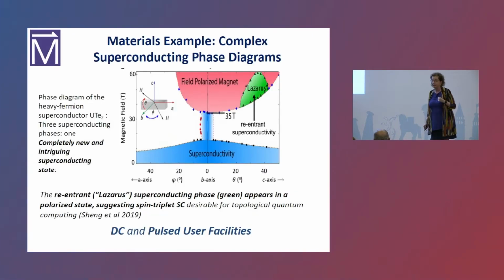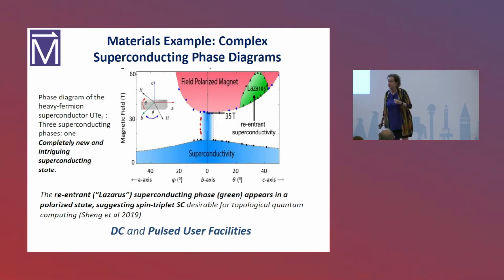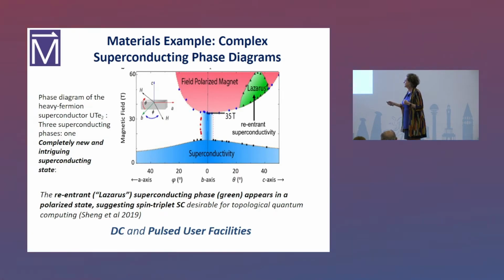So this is one that really just started a whole new field of research. It's this heavy-fermion, uranium-tellurium-2. And what was found was that, as many of you know, I'm not going to be giving a public lecture, I'm going to assume you know what a superconductor is, if you apply a field to a superconductor, you break the superconductivity. So we have here, as a function of angle in the uranium-tellurium-2, if you apply a certain field, this white area is where it's not superconducting anymore. Okay? And what's interesting at this angle, the superconductivity lasts up to 35 Tesla.